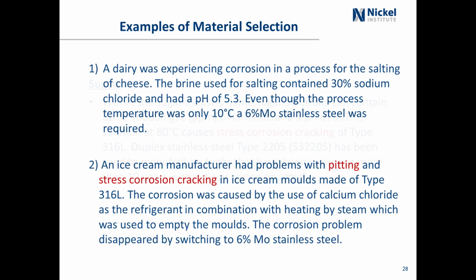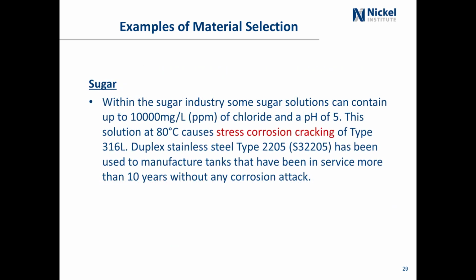And then in the production of sugar within the sugar industry, some sugar solutions can contain up to 10,000 parts per million of chloride and a pH of 5. Sometimes this solution is at 80 degrees C and can cause chloride stress corrosion cracking of type 316. But when duplex stainless steel type 2205 has been used to manufacture these tanks, they've been in service for 10 years and there's been no problems.